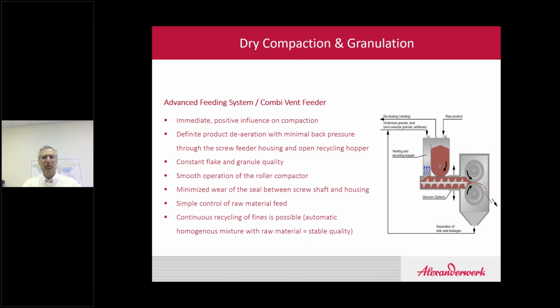In order to also enhance removal of the air from the product, we use vacuum at the end of the feed screw. The vacuum has a twofold benefit for the material. One benefit is obviously to aid in the deaeration, but the bigger benefit actually is to take the material and pull it out against the side of the feed screw housing. By doing that, the feed screw actually acts more as a metering screw. So instead of the material spinning with the feed screw, it's stuck to the outside of the feed screw housing, and as the feed screw passes by each single revolution, it grabs that material and then transports it right to the counter-rotating rolls. So using this technology, we have a very accurate transport system to the counter-rotating roll assemblies, giving you a very uniform product.